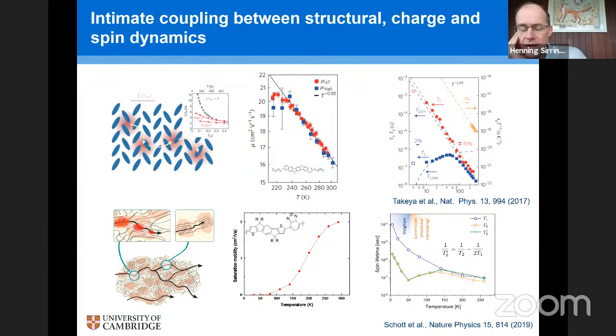So these are both ESR measurements. The spin pumping measurements that Angela did provide, of course, somewhat complementary and different information. If you take the lifetime from the ESR measurements plus the diffusion constant, do you get the spin diffusion length that is measured by spin pumping?